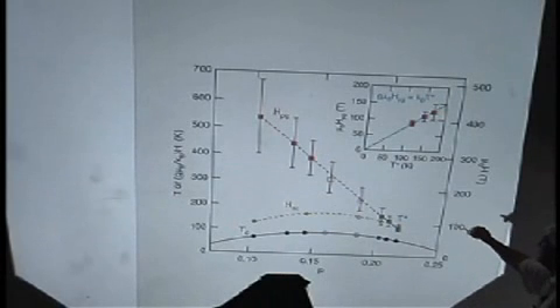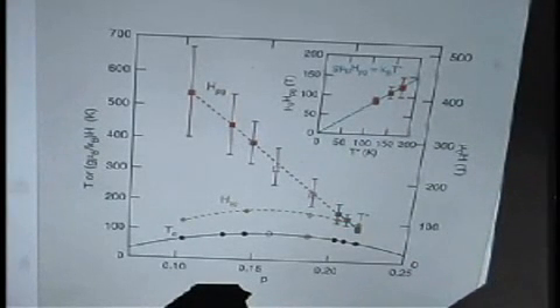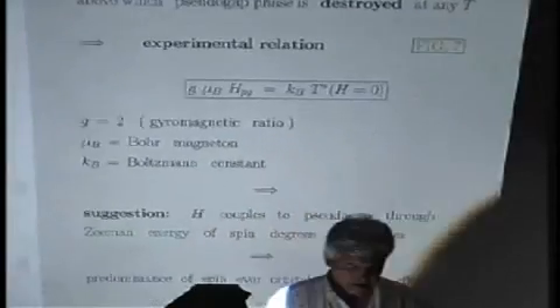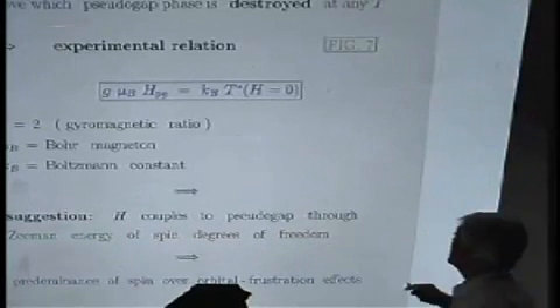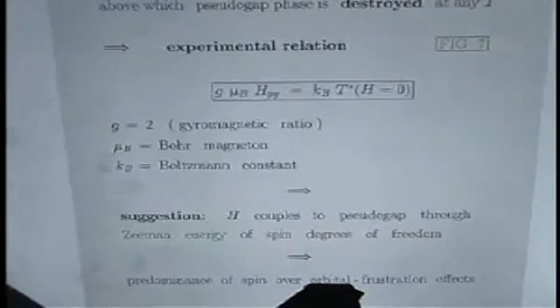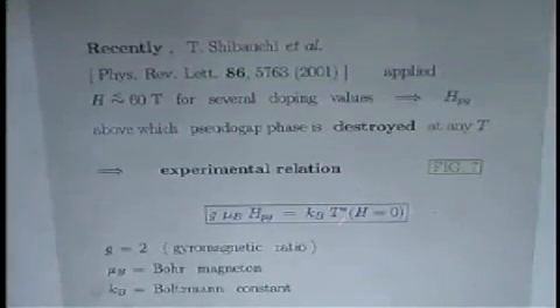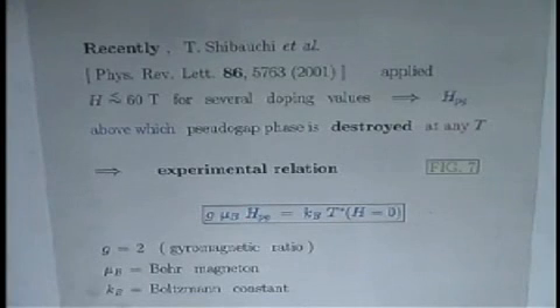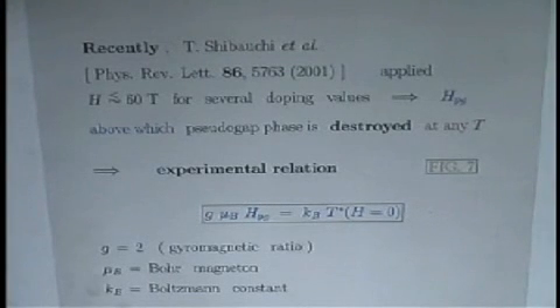Again, you see these two, this is a critical temperature, this will be this T star temperature, merging together in the overdoped region. But what is relevant is this inset here, where this pseudo-gap critical field is related to the T star at zero field. And you see a sort of linear behavior. Of course, you have to add this point here to go to experiment and theory. And they identified this simple experimental relation, sort of a Zeeman-like relation, where the critical temperature at zero field is connected with the pseudo-gap critical field, and it really looks like the spin degrees of freedom are the most relevant in this region.